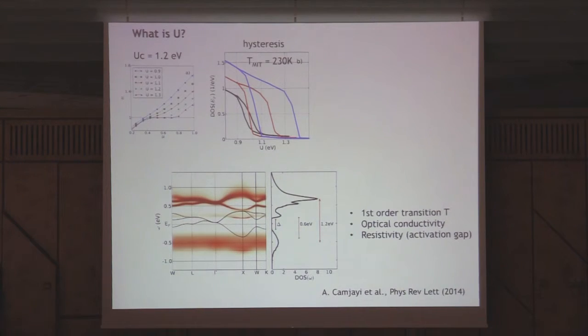So, of course, one of the problems with the LDA plus DMFT calculations is that we do not know reliably how to compute U. So then we put some physical input, and we know that applying a pressure to this system, we manage to get into a metallic state. So clearly, the U has to be such that places the system next to the Mott point. So what we did was start scanning through the values of U, considering U as a parameter, and see when we open the gap.